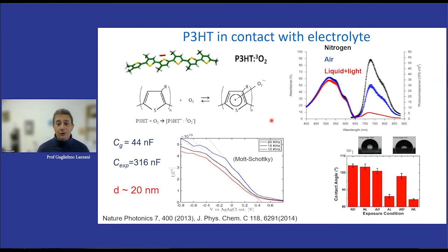You see that the surface is changing because, for instance, the hydrophobicity of the polymer, once it is in contact with water and light, or even just in water, is changing. There is a big change, and the hydrophobicity is reduced, so the contact angle is reduced. This suggests the role of the interface.